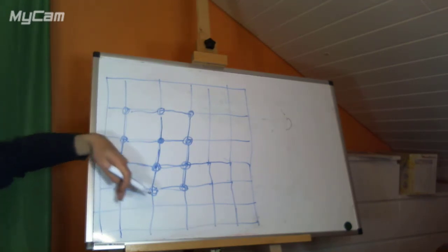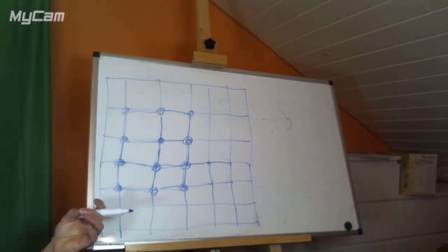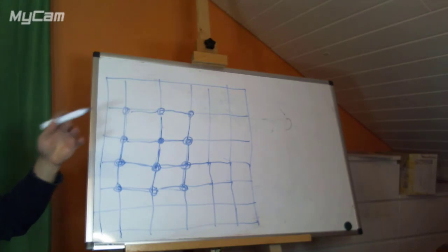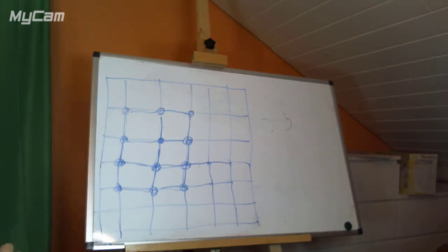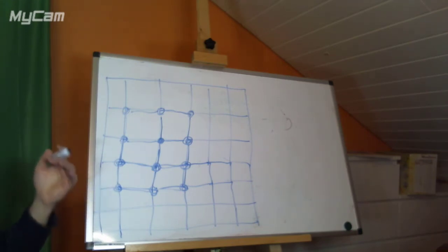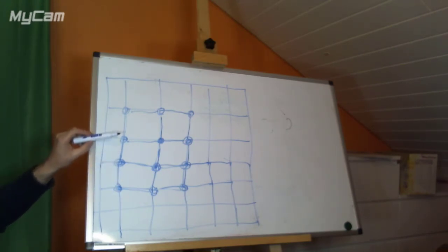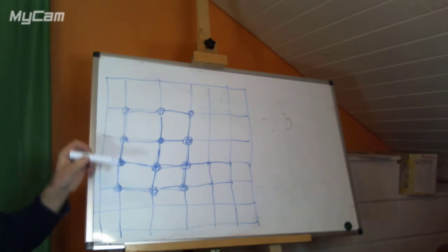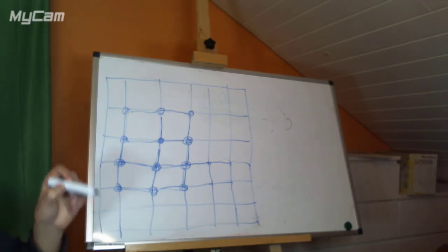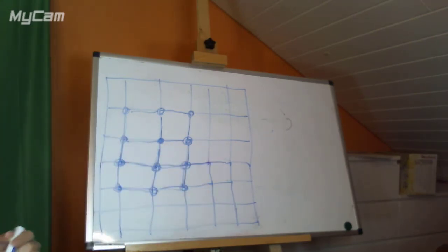Once we've completely filled the layer, we've got the same problem again, that there is nothing to bond it to, and so we discover that it is then harder again to add the next atom. If we do this in a vacuum and measure it very carefully, we can measure differences in the energy as we go through layers. So we add a first layer that is initially difficult, and then it becomes easy, and then we have a difficult bit again as we start a new layer because it has completely filled.